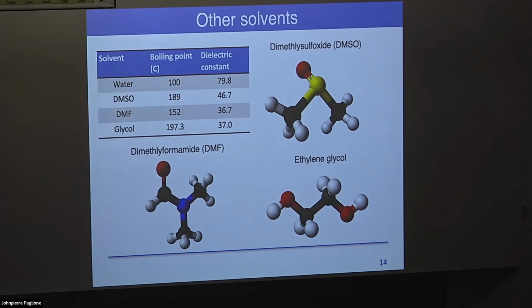Here are some other solvents that you might see in literature, with their dielectric constants and boiling points listed. The important thing, not just for hydrothermal but for any solvent, is that to get above 1 bar of autogenous pressure, you need to go above the boiling point of whatever solvent you have. So if you're using DMSO, for example, you need to go above 189 C to have an autogenous pressure of more than 1 atmosphere. The dielectric constants are all labeled at room temperature, but they would change at different temperatures, maybe not as drastically as water. These are some different solvents you might see listed in the literature for solvothermal synthesis.